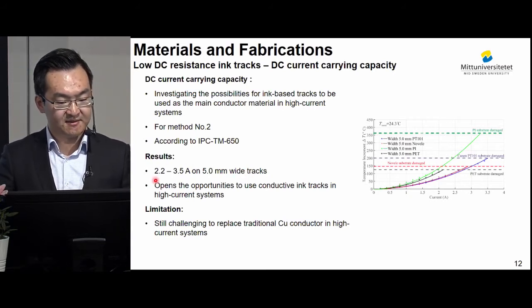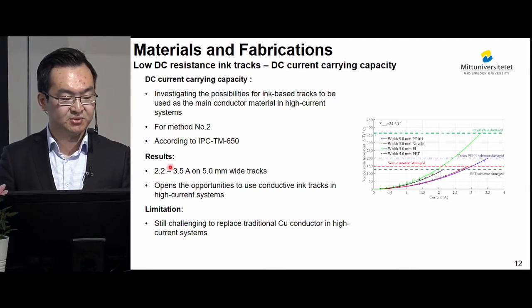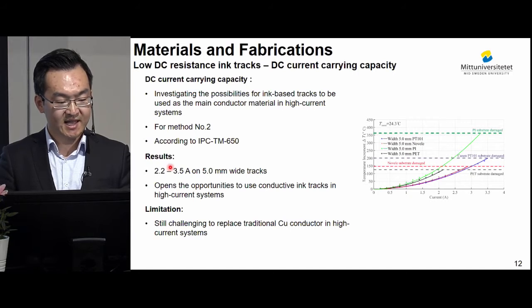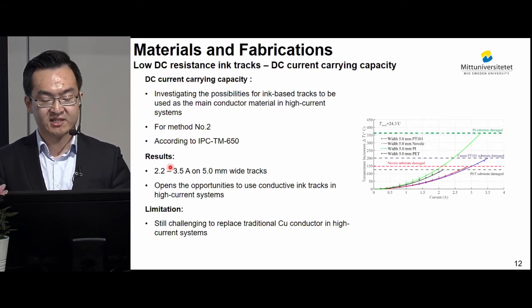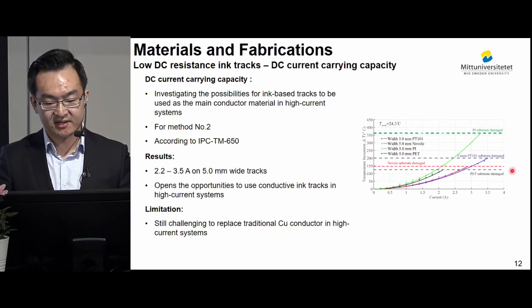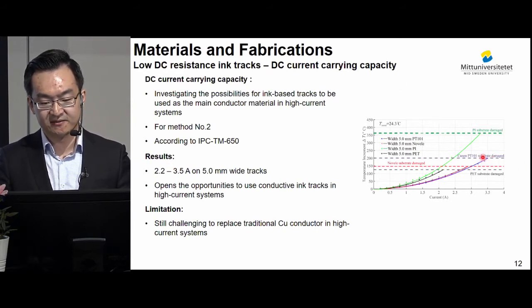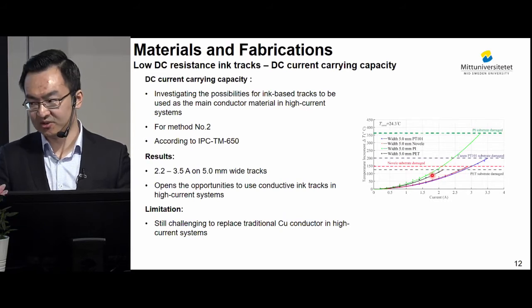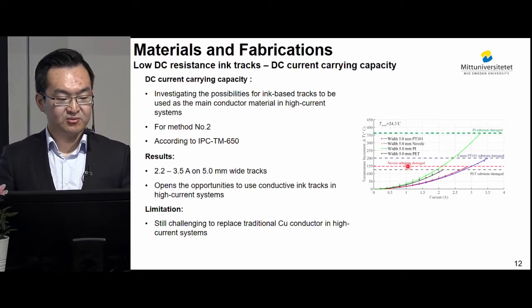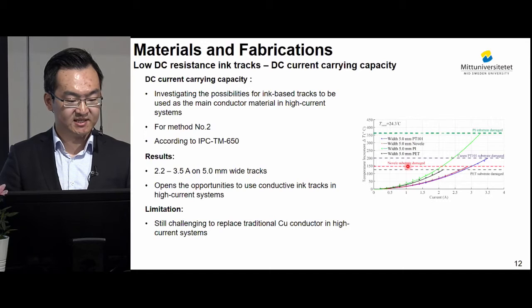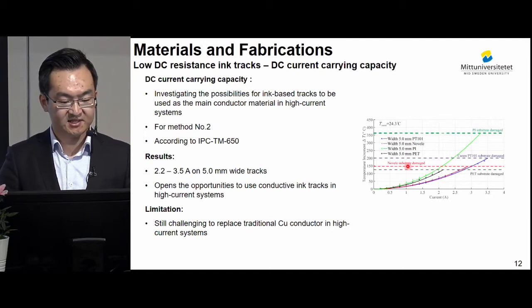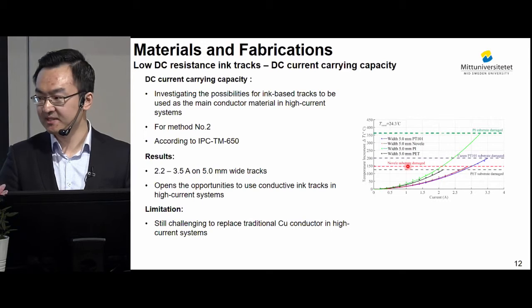And the results showed that a current carrying capacity between 2.2 to 3.5 amps on a 5.0 millimeter wide track was achieved, where the highest capacity was achieved on photo paper, followed by tracks printed on polyimide, coated plastic and uncoated plastic. The result of this test showed it is possible to use conductor ink tracks in high current systems.